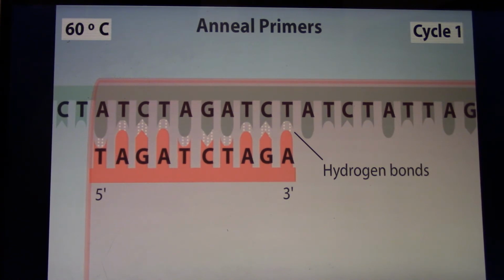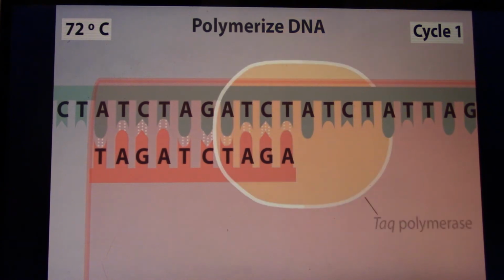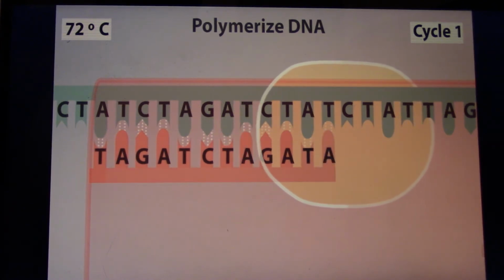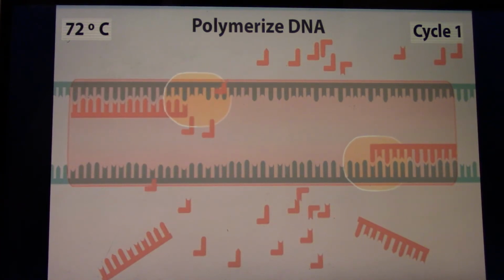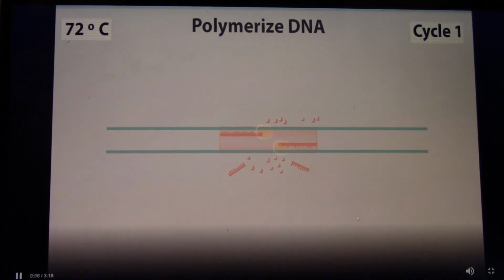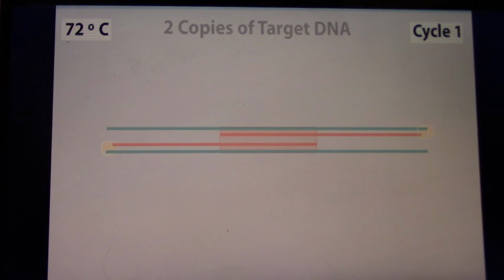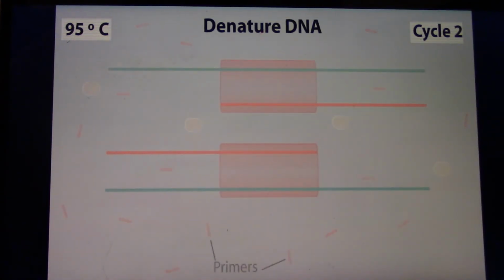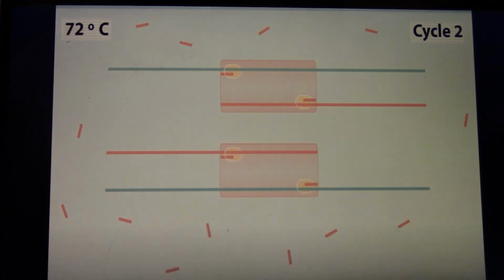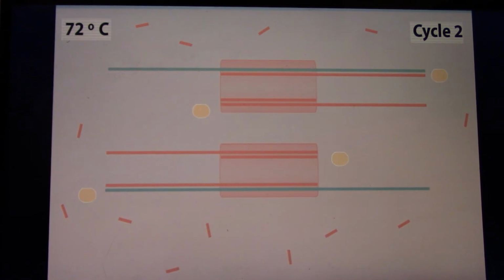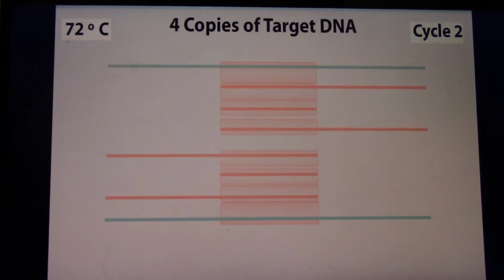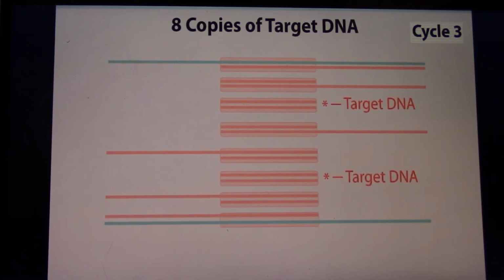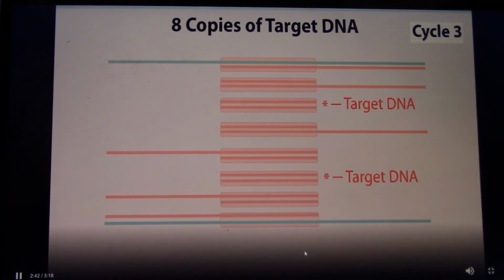In the next phase, the temperature is raised to 72 degrees Celsius. Taq polymerase functions optimally at this temperature and begins polymerization, adding nucleotides to the 3' end of each primer attached to the DNA strand. After one complete cycle, there are 2 double-stranded copies of the target DNA. The PCR reaction mixture contains many copies of the primers and an abundant supply of nucleotides to perform many additional cycles. After a second cycle, there are 4 copies of the target DNA. After cycle 3 is finished, there are 8 copies of the double-stranded target DNA sequence. Note that only 2 of the double-stranded copies consist of just the target fragment. The others also include flanking DNA regions.